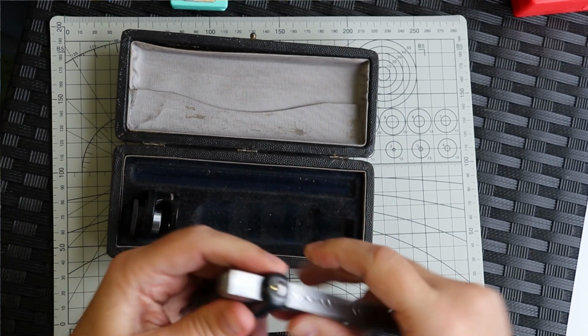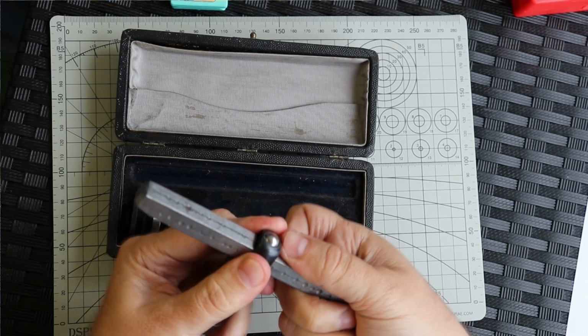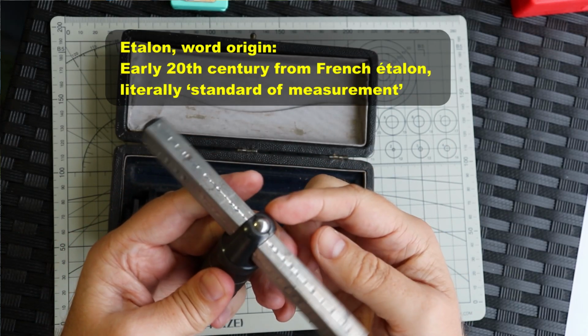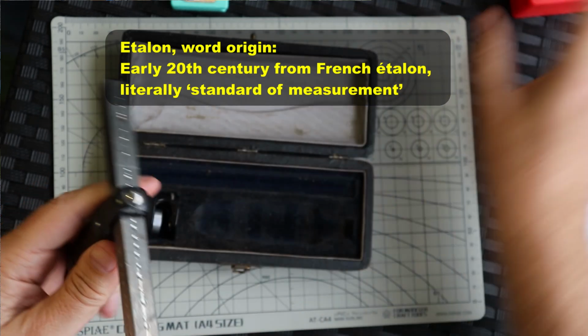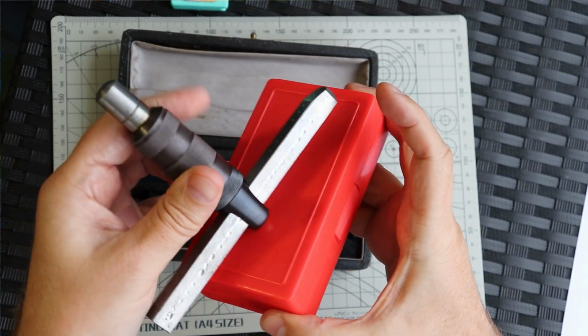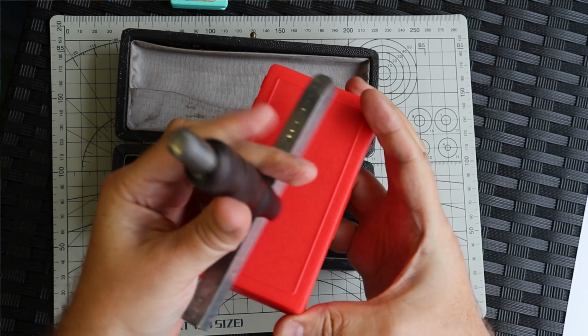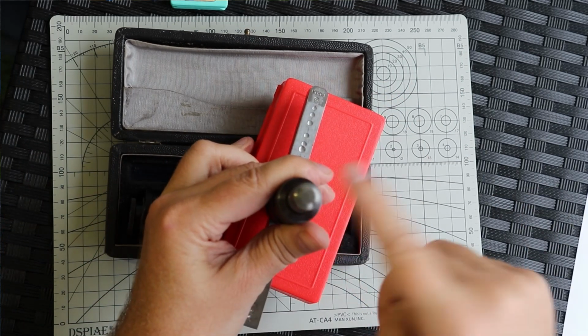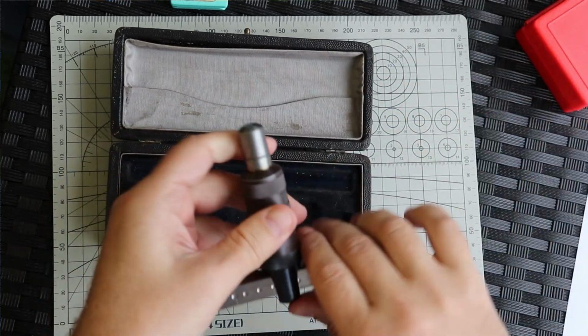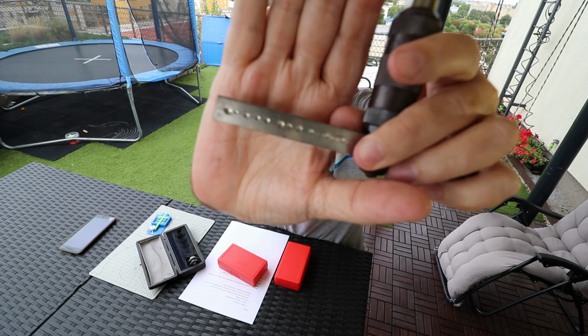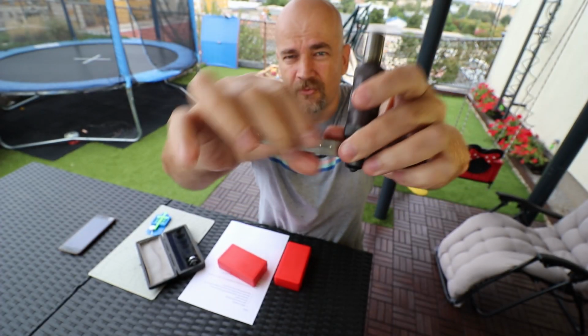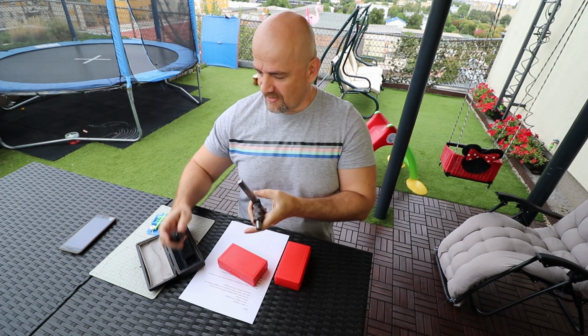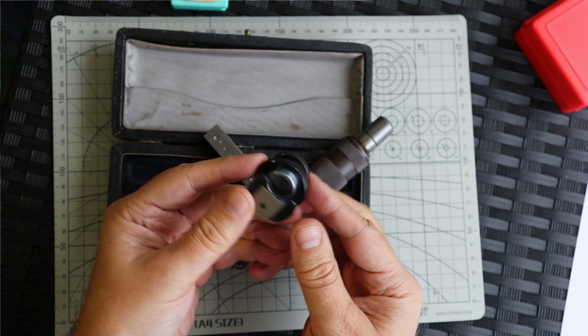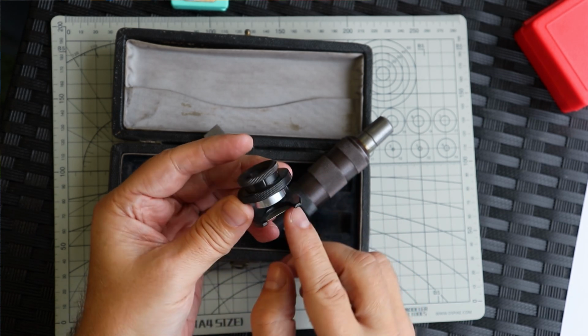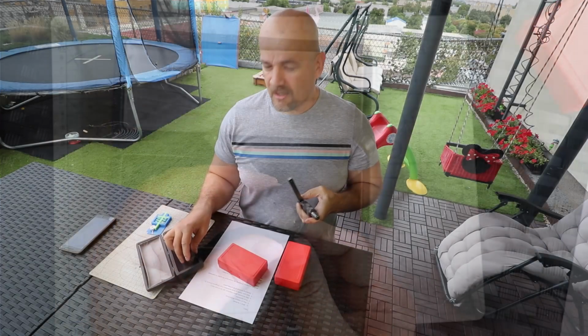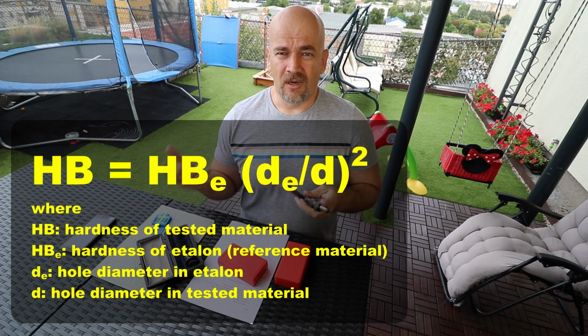Here we have this steel ball, and we need an etalon, which is some metal with a known hardness. We have to place it inside, and then place it on the testing material, which is metal, of course, hit it with the hammer, and we will get two holes. One hole in the tested material and the other in the etalon. Maybe some holes are visible already on this etalon. It is full of holes. We can measure the diameter. Actually, in this set it is a small micrometer with a ruler of 0.1 mm precision. And then using this equation we can calculate the hardness of the testing material.